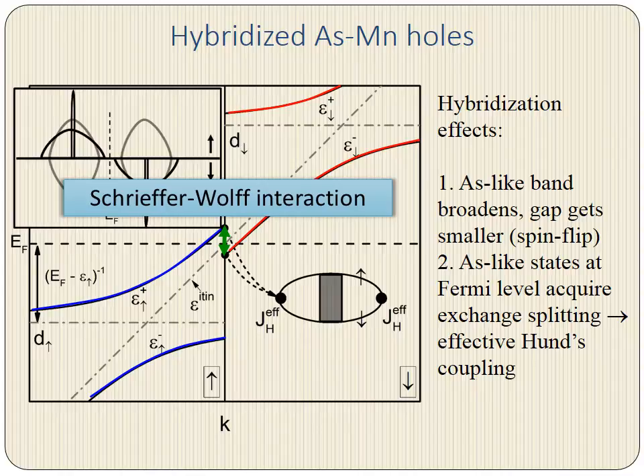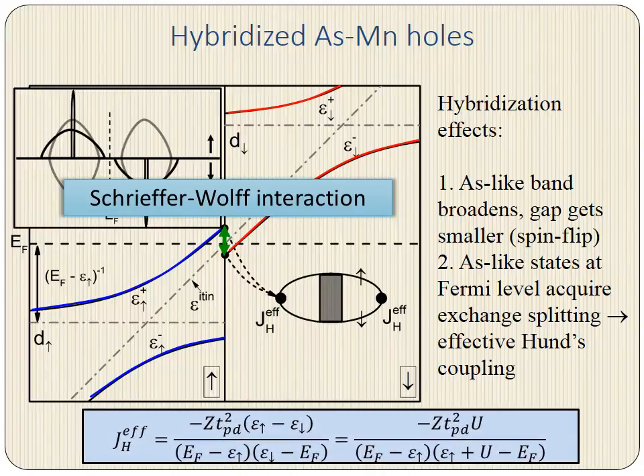Again, the polarization at the Fermi level can be described by the same Feynman diagram, with the key difference being that the vertices are now effective couplings described by the Schrieffer-Wolff theory, and given in the formula below. We should also note that the polarization of the arsenic states is in a direction opposite to what you see for manganese. This means that the vertices will each pick up a negative sign. In the end, though, this will not matter, because we're going to multiply each of the vertices together, everything will be squared, and so any minus signs will drop out.